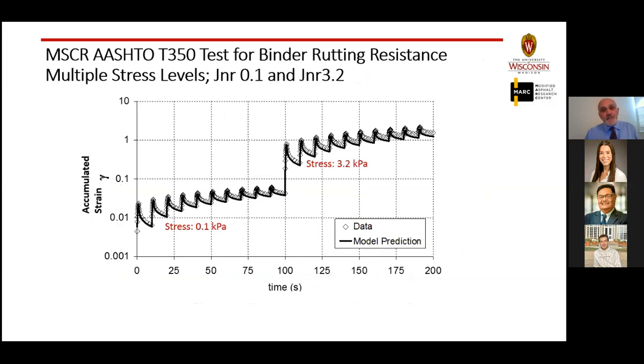I just mentioned that it's been 20 years since these concepts were discussed. The answer is yes. And it really moved so quickly, in my opinion, if you look at the asphalt specification history. Now we have a new test called the MSCR, Multiple Stress Creep and Recovery. And if you look at the MSCR, you will immediately recognize that the strain we're going to is much, much higher than the normal strain that you usually see. Here's an example. This is actually 10% strain. This is one order of magnitude higher. So this is 100% strain.